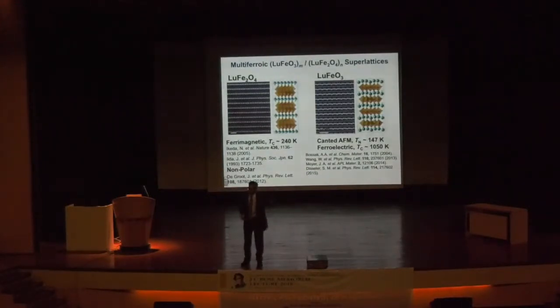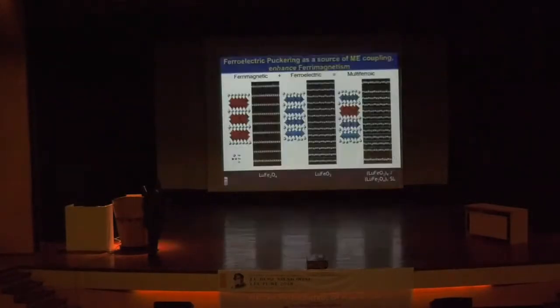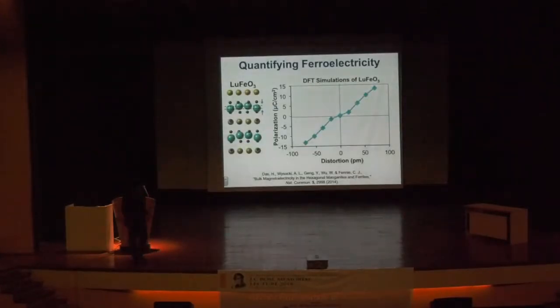And that structural degree of freedom couples to the charge, and the charge becomes a slave in some sense. So our thinking in this work, which got published in Nature a year or so ago, was to take this ferrimagnetic phase and couple it to the ferroelectric phase and create a multiferroic where the coupling is through the puckering of the 2 up and 1 down kind of layers. And indeed, that happens. I'm going to quickly show you the data before we finish up.